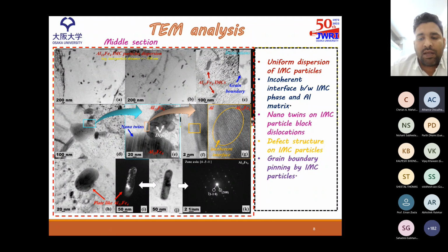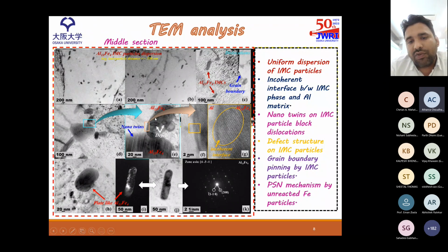Now, as I said, these small size IMC particles contribute in the grain boundary pinning, as can be seen here, and also here. The grain boundary pinning and the dislocation blockade can also be visualized here. The PSN mechanism by unreacted Fe particles is also visualized in some of the cases.